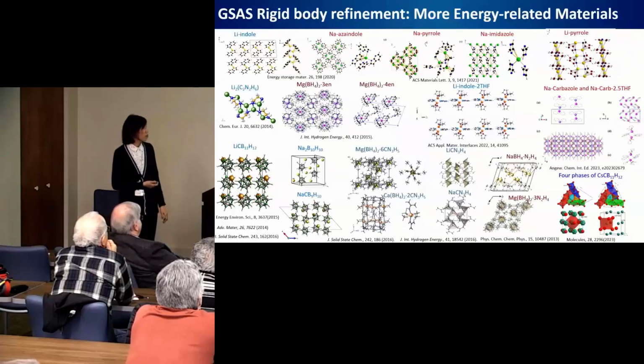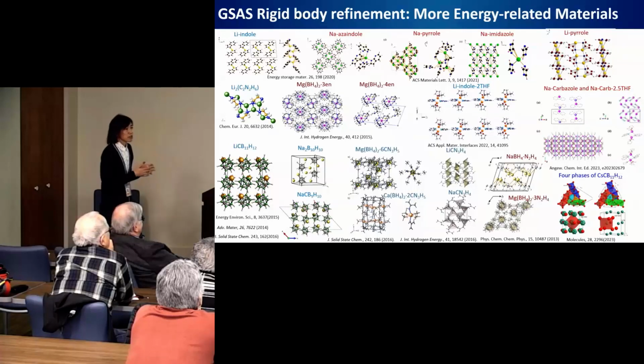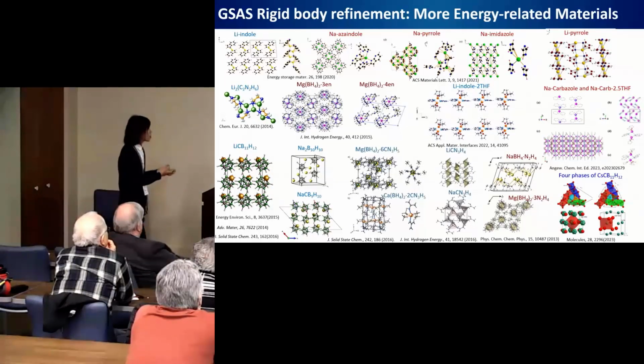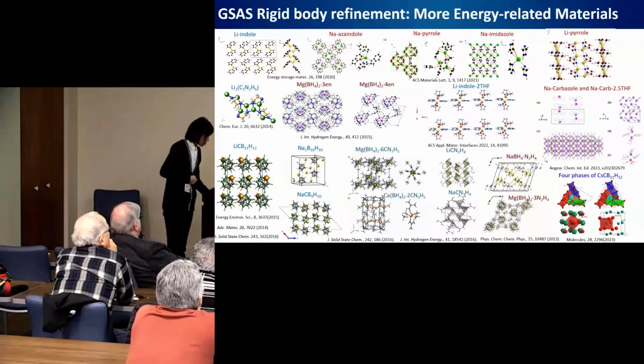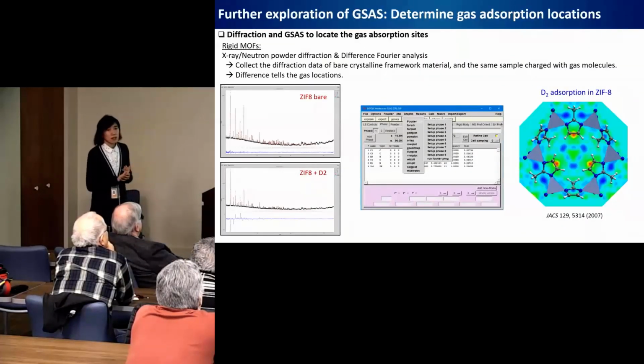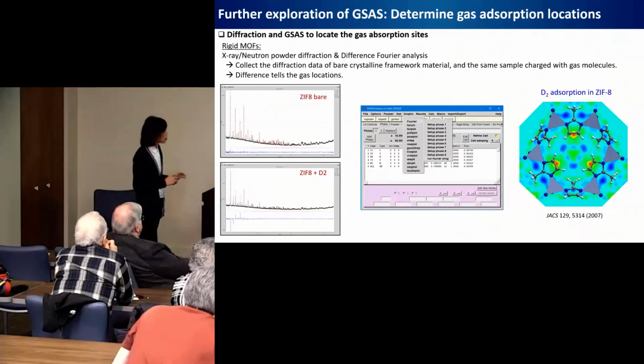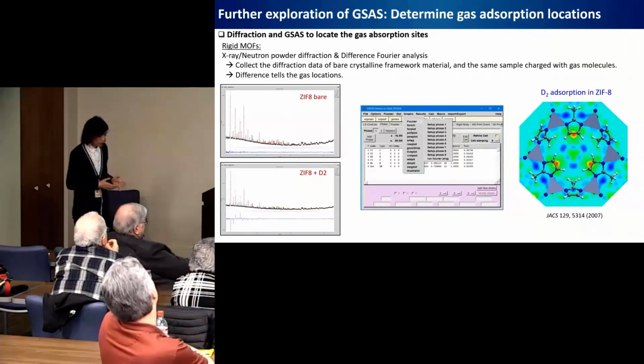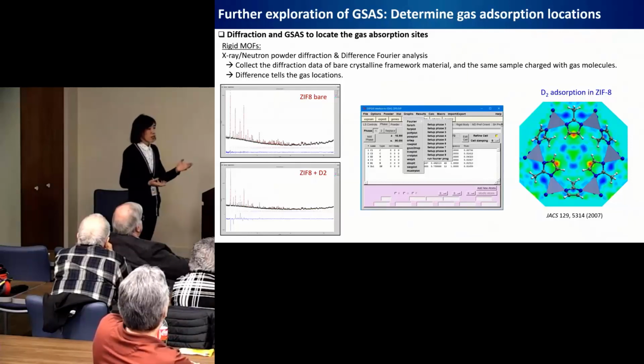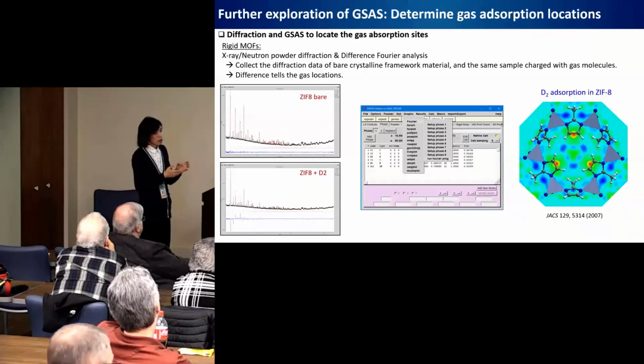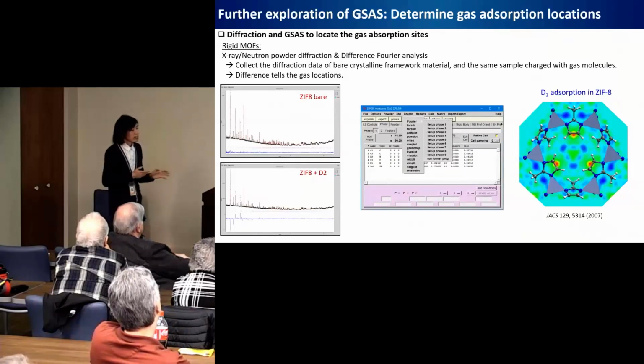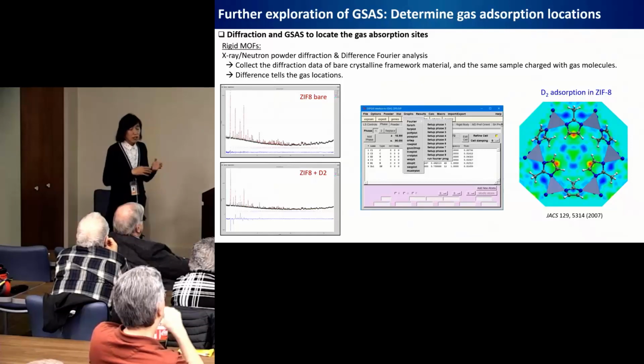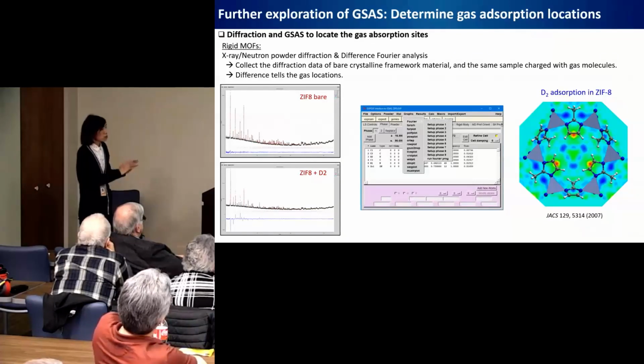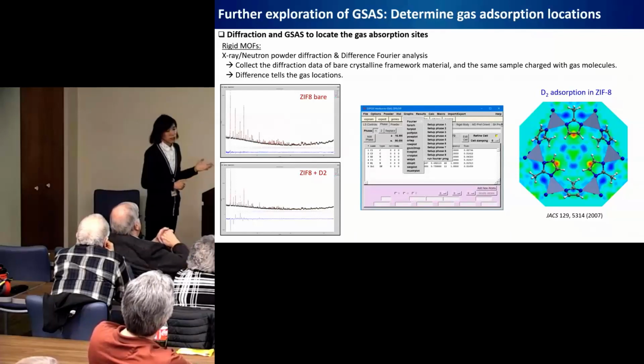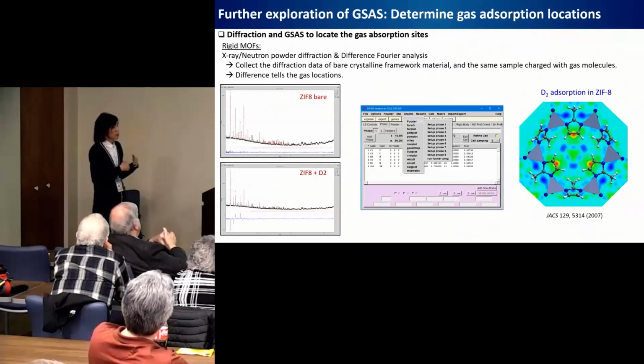And here are just a few more examples of various materials that we developed, and we determined and refined the structures using GSAS. So besides the hydride materials, we were also working on some porous crystalline framework materials for various gas absorption related applications. So we're interested in the structure of the framework materials themselves. For example, we can refine the structure with proper rigid body constraints on those ligands, organic linkers. But we are also interested in determining the absorption site of small molecules within those frameworks. So usually to do that, for rigid frameworks, the process is very straightforward.